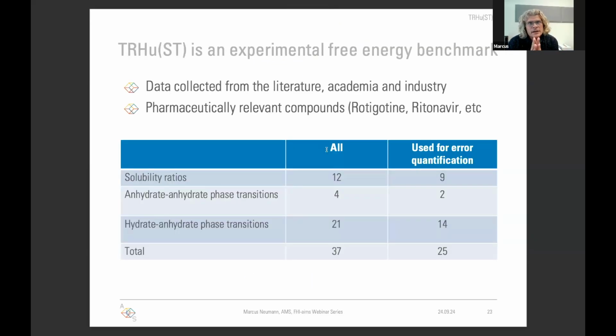So for the moment, I have only talked about trust as an energy calculation method, but trust is also a free energy benchmark. So we have done a lot of work with our academic partners and also with our pharmaceutical customers to get our hands on reliable free energy differences for industrially relevant compounds. And in total, we have collected 37 free energy pairs. 12 of them come from solubility ratios. So two polymorphs, if you measure their solubility in a solvent where they are poorly soluble, so you are almost in infinite dilution, then the solubility ratio is actually related to the free energy difference between the two forms. Then we have four anhydrate-anhydrate phase transitions as a function of temperature, and we have 21 hydrate-anhydrate phase transitions as a function of relative humidity.